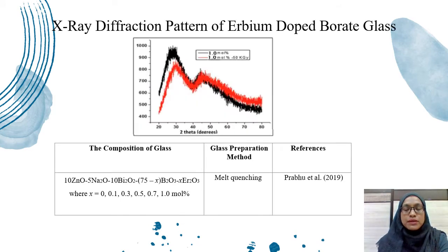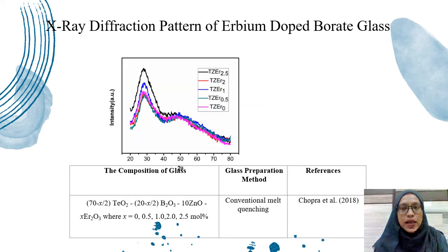In the XRD pattern by Prabhu et al. 2019, the result obtained did not indicate any sharp peak, as shown in the figure, which verifies the amorphous nature of the glass. Lastly, by Chopra et al. 2018, the figure shows the XRD pattern has a large hump.